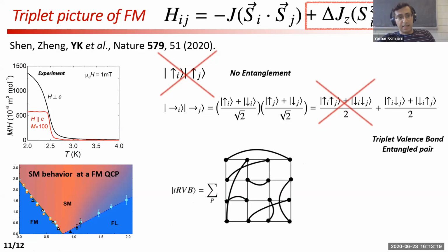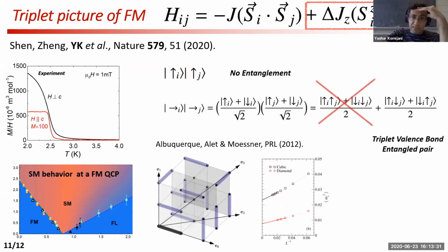Now, I think a question that we should ask is, would such a state show any sign of long-range order? And I have to remind you of this work by Roderick Moessner and coworkers, where they tried, in the anti-ferromagnetic context, a state made of short-range singlets on a cubic lattice. And they showed that in the limit of large system size, so when this 1 over L goes to 0, there will be a finite intercept for the staggered magnetization. So even a short-range singlet covering can show long-range order.